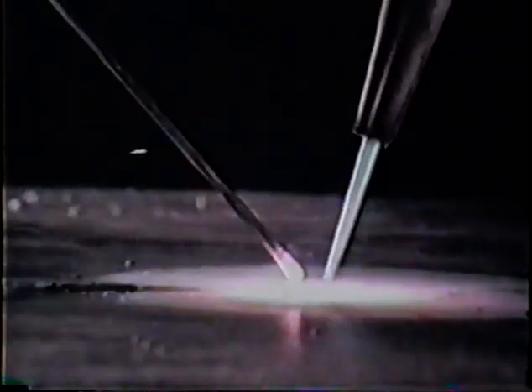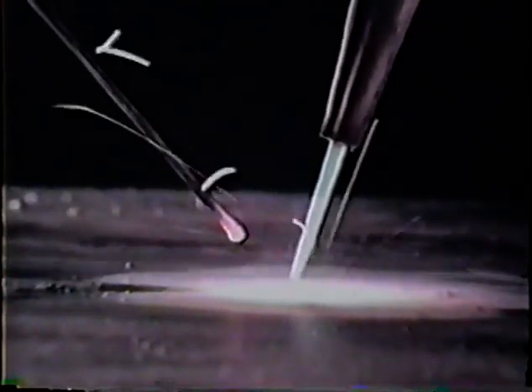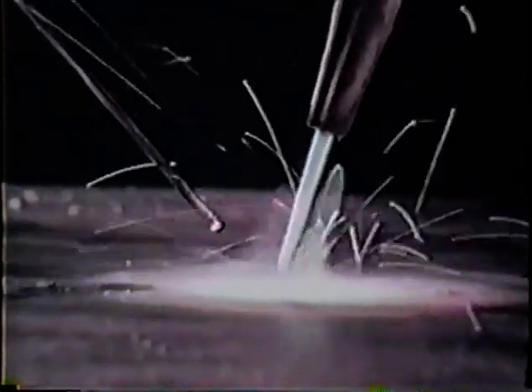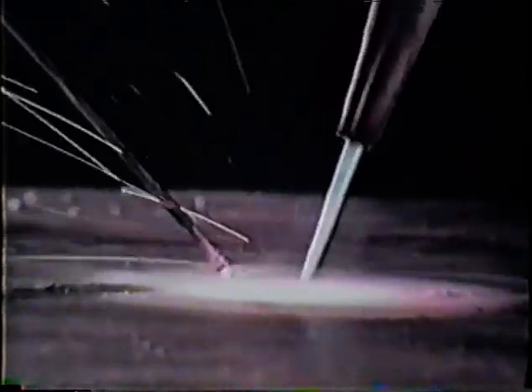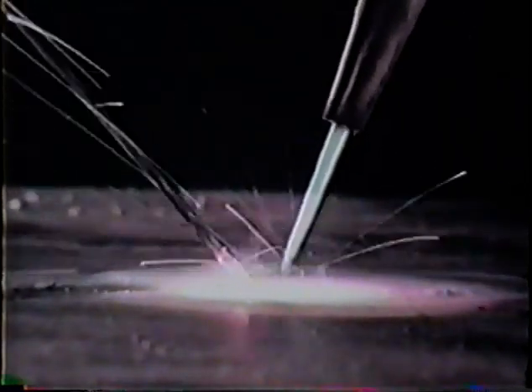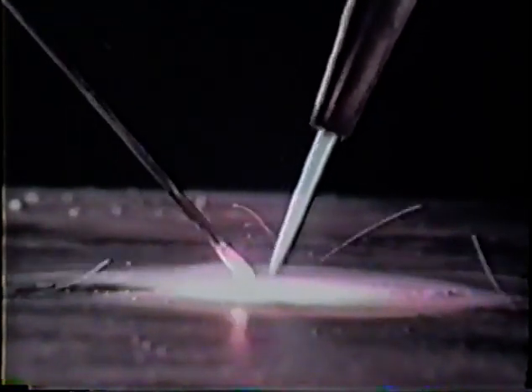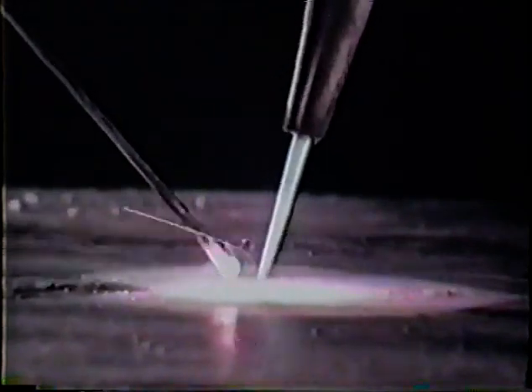The edges of this weld are not fused to the plate. This is because the plate's edges were not hot enough and therefore didn't melt and fuse with the filler rod. To rectify this problem, decrease your welding speed to ensure the base metal puddles, or increase your torch angle so that it delivers more heat to the area.